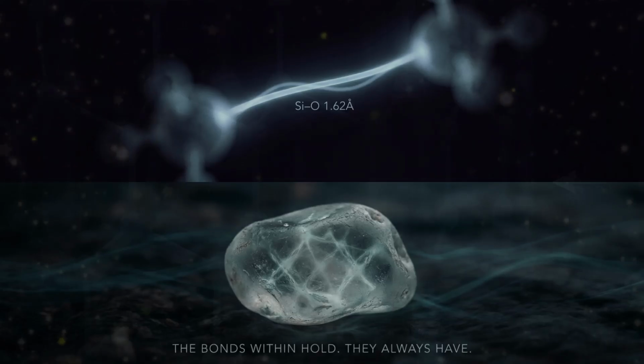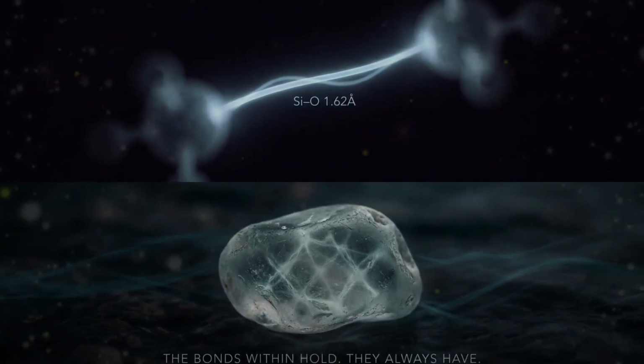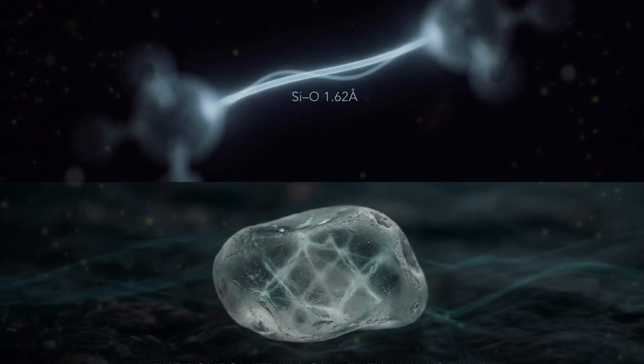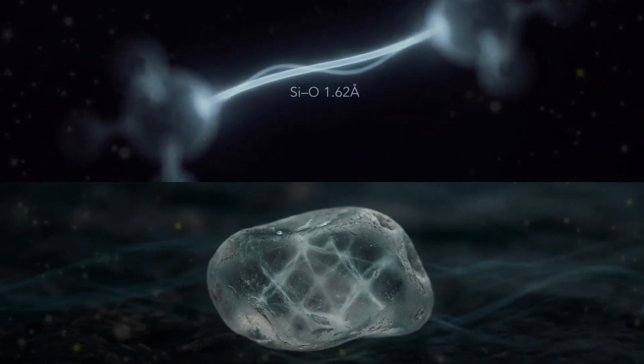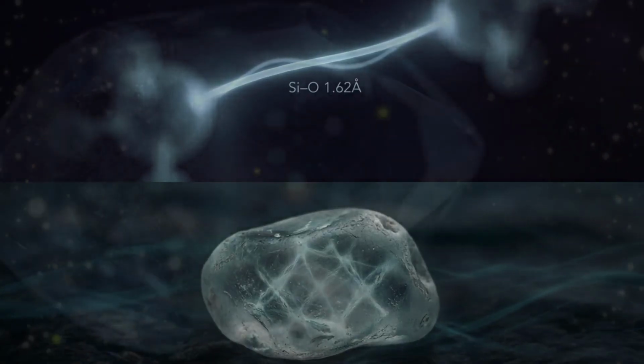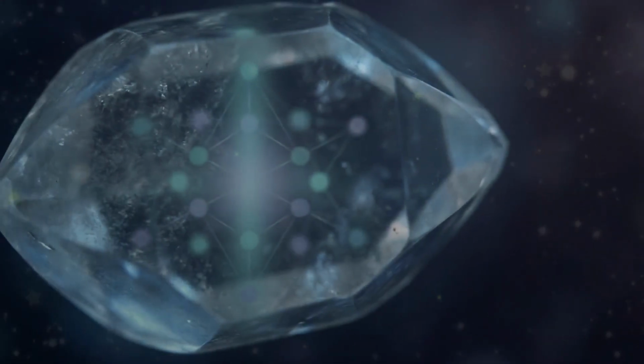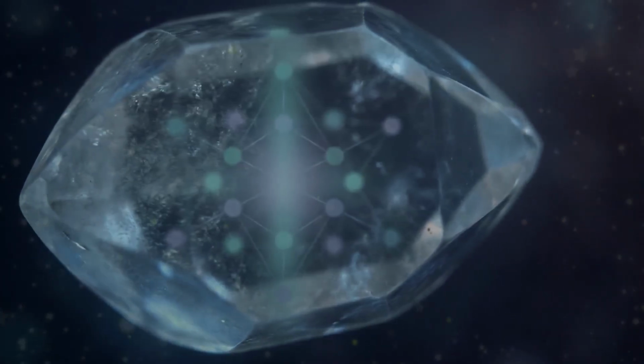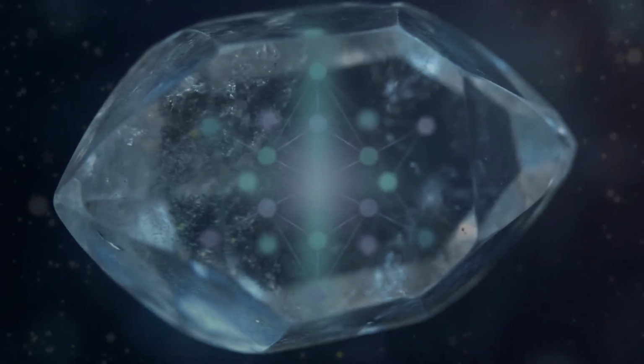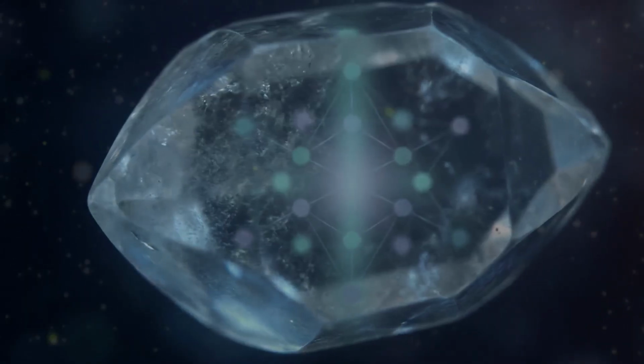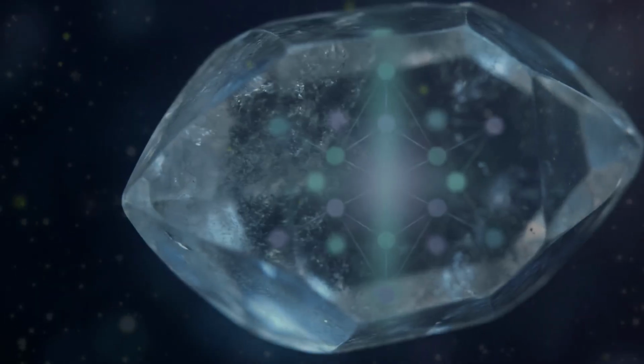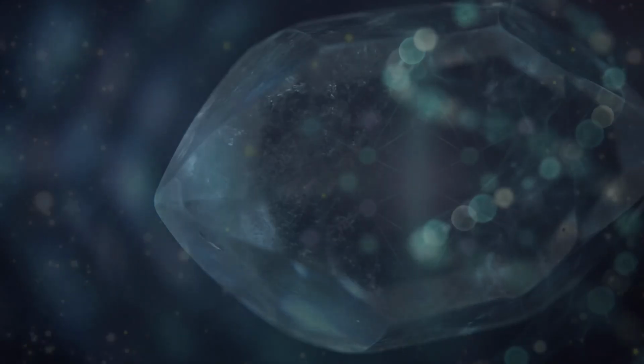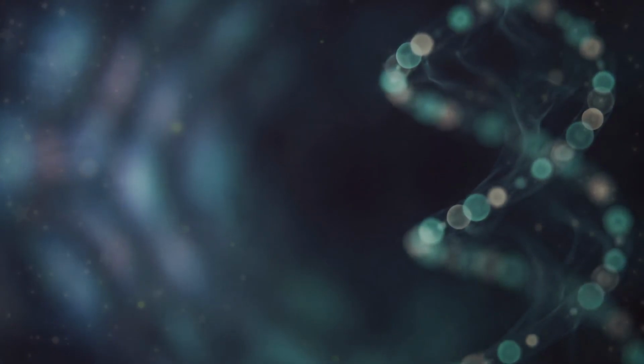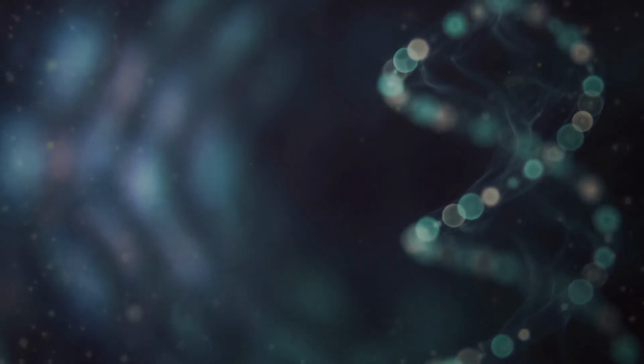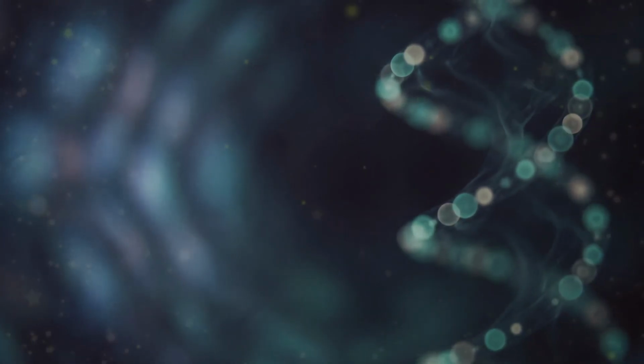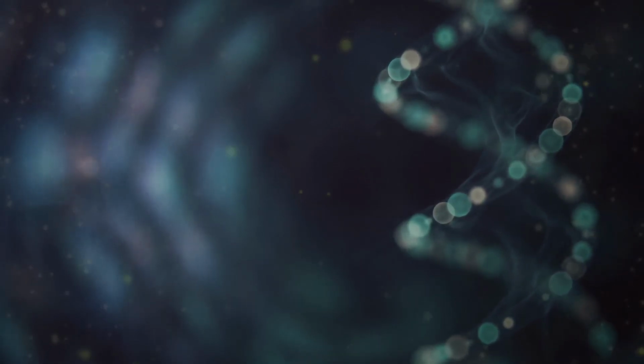The piezoelectric effect in quartz arises specifically because the crystal lacks a center of inversion symmetry, the geometric condition in which every atom in a unit cell has a corresponding atom in the identical position on the opposite side of a central point. When a crystal with inversion symmetry is deformed, the positive and negative charge centers within the unit cell move symmetrically, and the net electrical effect cancels out. The helical arrangement of silicon and oxygen atoms in quartz breaks that symmetry. Deformation displaces the charge centers unequally. The resulting charge separation across the crystal face, the piezoelectric voltage, is proportional to the applied stress. The relationship is linear and reversible. Doubling the stress doubles the voltage. Removing the stress removes the voltage.